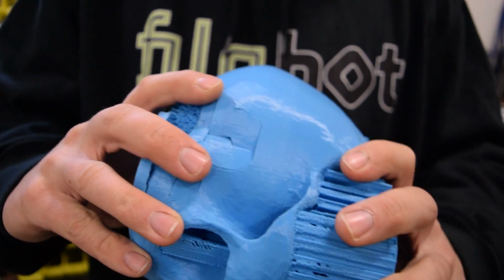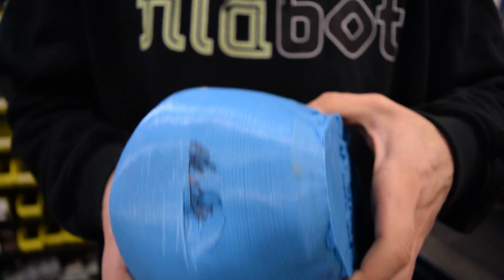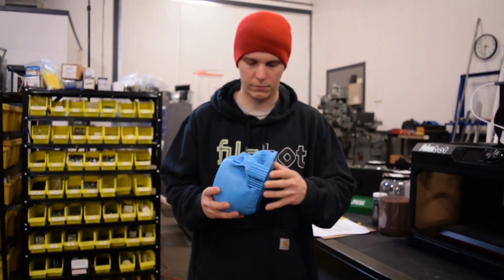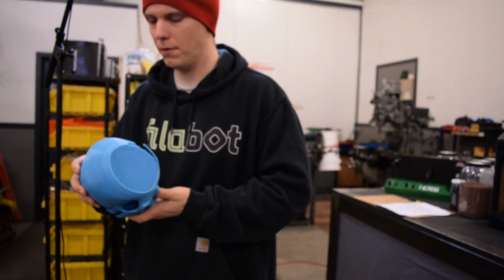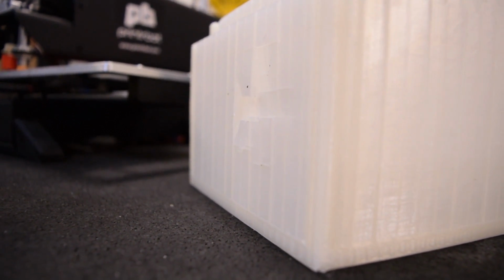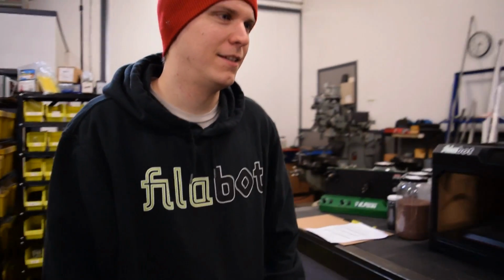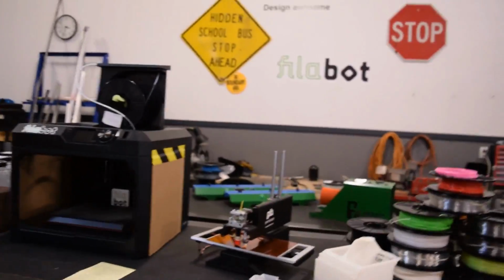So that's the main issue we focus on. When we make filament, we're always shooting for the plus or minus 0.05 millimeter tolerance. And for most layer heights, that's pretty acceptable quality. For 1.75 millimeter filament, that's around 2%. So that's a 2% variance in the volume that's coming out of your extruder.